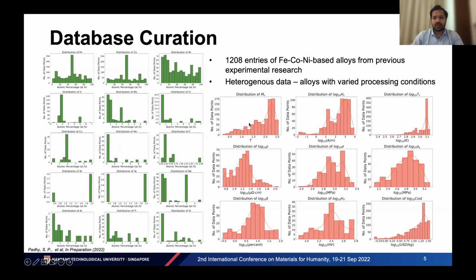Now, for the properties, we collected magnetic properties such as MS, HC, and TC, electrical properties such as electrical resistivity, and mechanical properties such as tensile strength, yield strength, elongation, and hardness. Further, we also calculated the cost using the raw material or the elemental cost of the elements present in the database. As you can see here, except for MS, all other properties were taken in log 10 scale. This is to reduce the skewness and also to make the range of the properties at the same level.